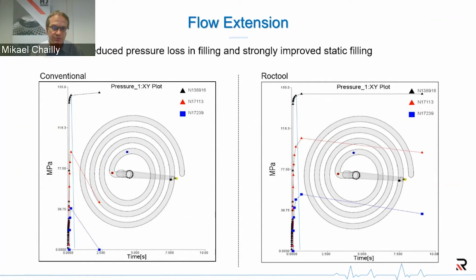What is also of importance is to note that when we do this static filling, in conventional molding you've got a drastic pressure drop onto the sensors located within the cavity, whereas in Roctool conditions you can still fill your mold and have a higher pressure within the cavity thanks to this hot mold surface. So you are able either to continue the filling or to pack efficiently if you were working on a real part.